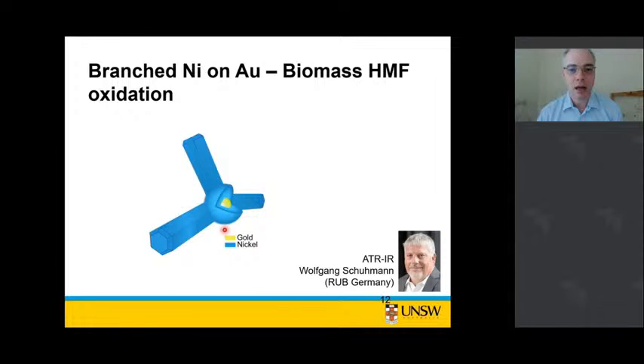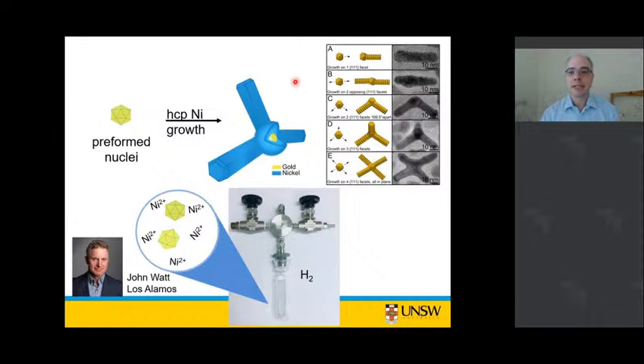So this project is looking at having gold seeds again as our face-centered cubic seed, and then having nickel as a hexagonal close-packed structure arm coming off our gold seed. And this is in collaboration with Wolfgang Schumann from Bochum, and he does a lot of the catalysis with us. So this was looking at nickel for biomass oxidation. So as I said, with the pure nickel, we could get branch structures, but we didn't really get the control that we were after.